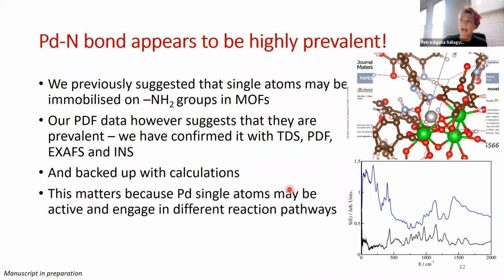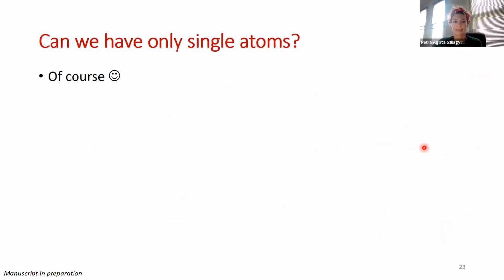And this is relevant because this material in particular had been looked at for quite a number of catalytic reactions. In particular, it's been looked at for C-C coupling reactions, which we know that palladium single atoms are also active in, and it's never been hypothesized beforehand that the single atoms may be doing the job here. So there is maybe a significant amount of revision of this body of work that's needed.